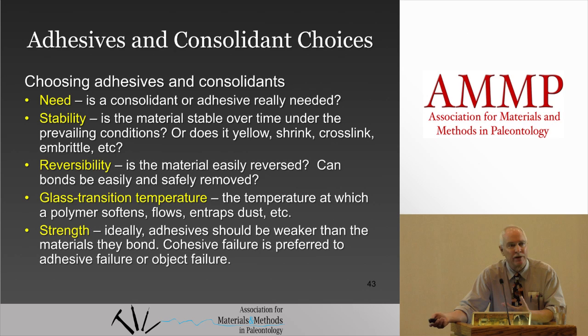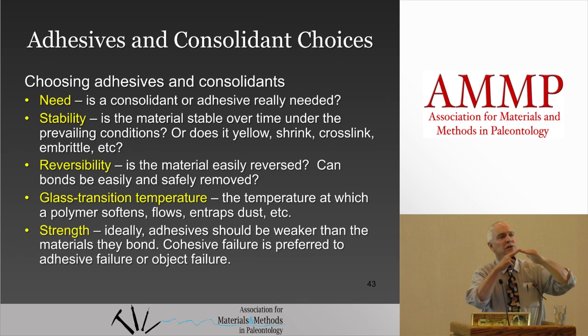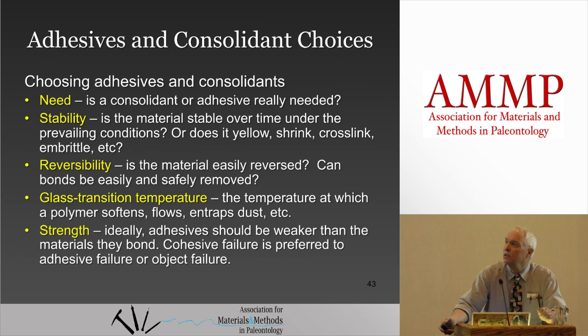Glass transition temperature. All I'll say about that right now is that any polymer that you use on fossils has a glass transition temperature, and that's a temperature at which the polymer is transitioning from a solid to a liquid. It's behaving more like a glass, which is a very viscous liquid. If you reach the glass transition temperature of a polymer, if you're using it as an adhesive, it can flow. The join can just basically bend if the specimen's not supported properly. It can entrain dust. You've all seen shellacked fossils that are now covered with shellac and dust. Shellac has a notoriously low glass transition temperature.